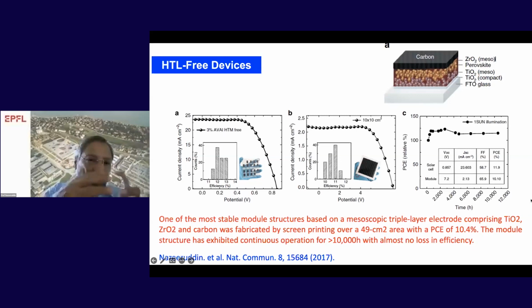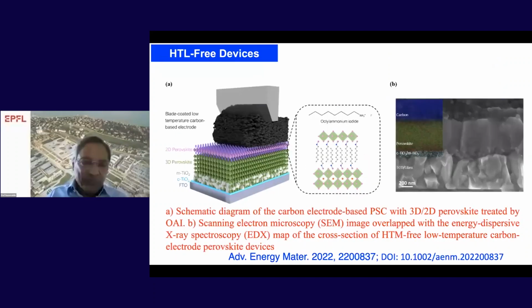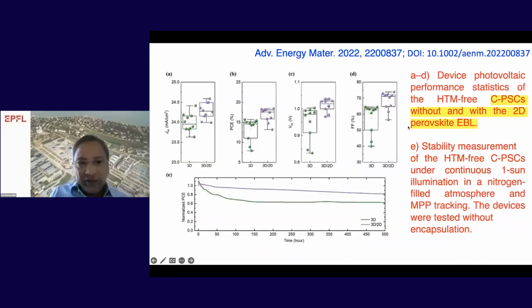Since we have the knowledge of reducing the interface recombinations by two-dimensional perovskites, can we combine our previous knowledge of the two-dimensional perovskites with the triple layer configuration? That was the study. So there is no hole transport material here. You can consider the two-dimensional perovskite acts as a hole transport material followed by the carbon. This triple layer configuration gives us an efficiency of 18% with the two-dimensional perovskite, without it in the range of 15%. And the stability with the two-dimensional perovskite on top of hole transport material free devices is significantly enhanced compared to without two-dimensional perovskites. So these are the hole transport material free configurations.